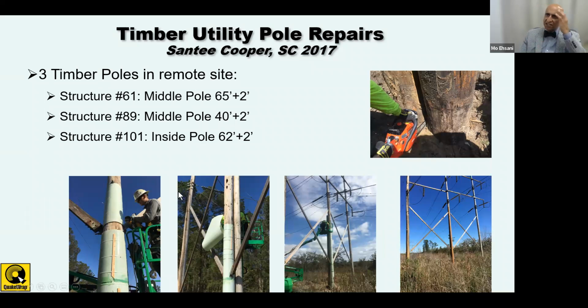In this particular site, there were 3 of these at different heights and so on. But I wanted to point out that, as you see in the upper right picture here, when you have 2 of these poles very close to each other, you can run a saw along the connecting point and create a 1/8 or 1/4 inch gap between these 2, and then the jacket can pass through that little opening and create a shell around the deteriorated pole to fix it. So this is another application.